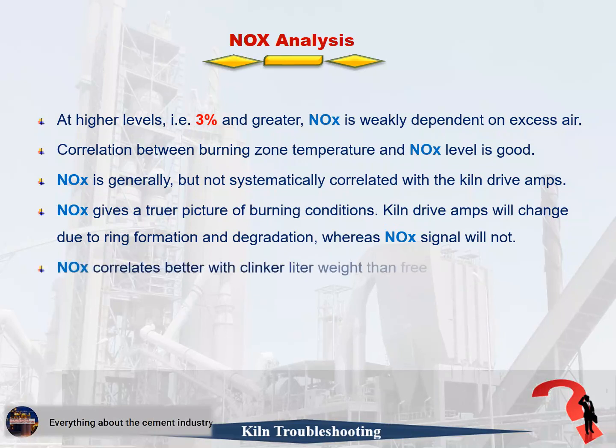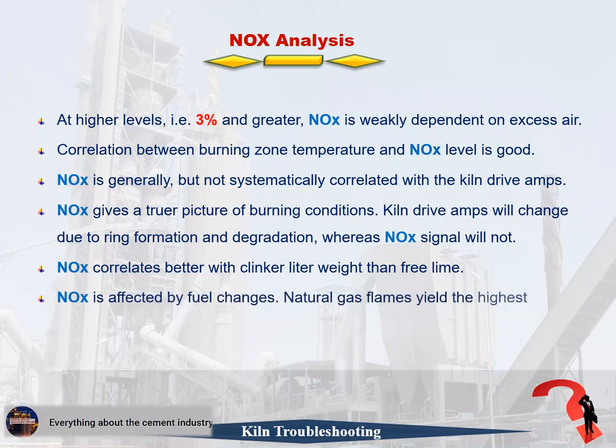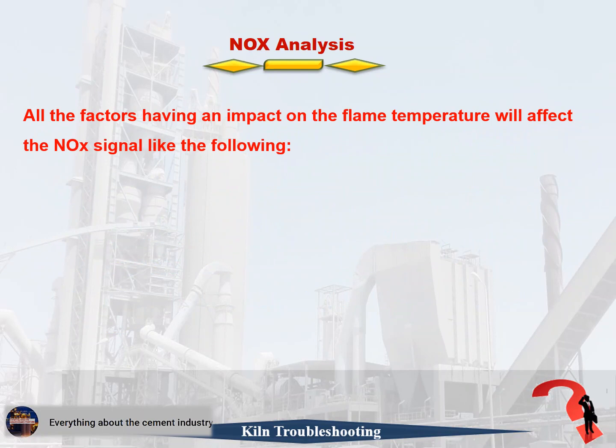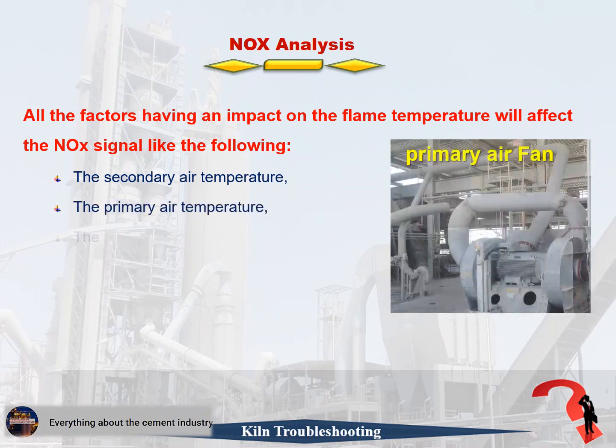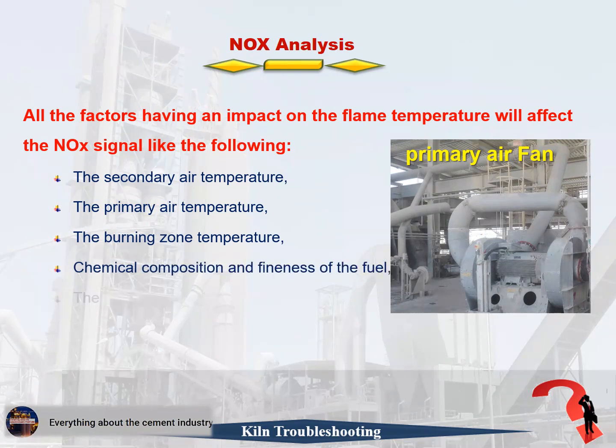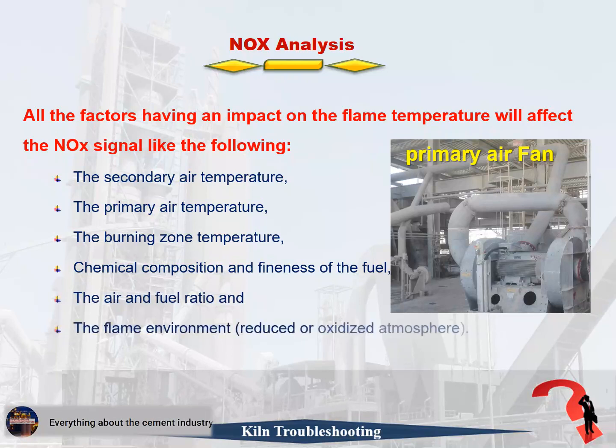10th, NOx correlates better with clinker liter weight than free lime. 11th, NOx is affected by fuel changes. Natural gas flames yield the highest. 12th, NOx level: all the factors having an impact on the flame temperature will affect the NOx signal, like the following: the secondary air temperature, the primary air temperature, the burning zone temperature, chemical composition and fineness of the fuel, the air and fuel ratio, and the flame environment, reduced or oxidized atmosphere.